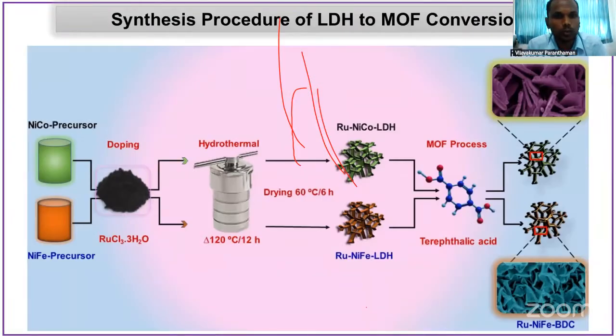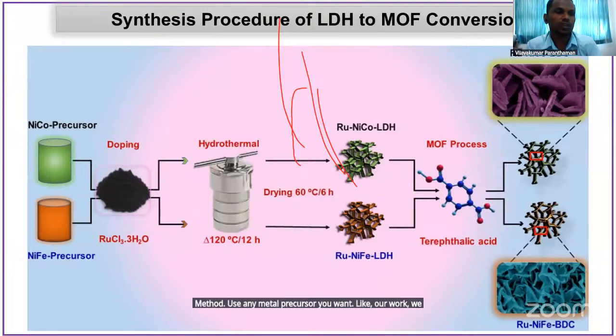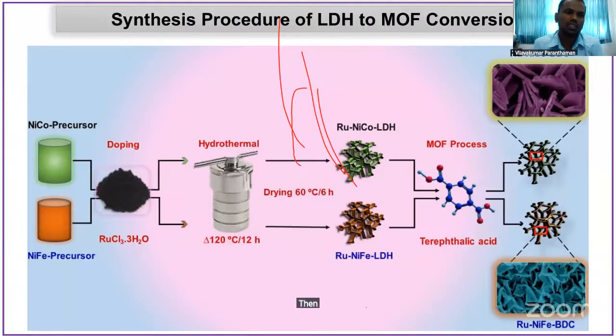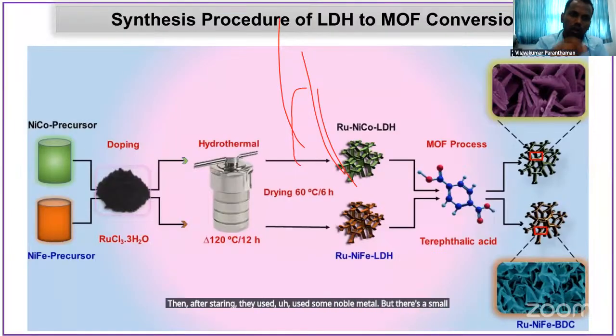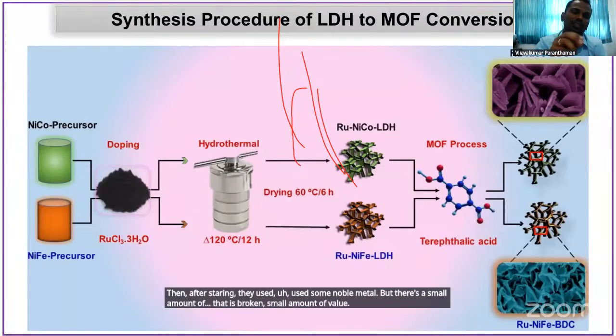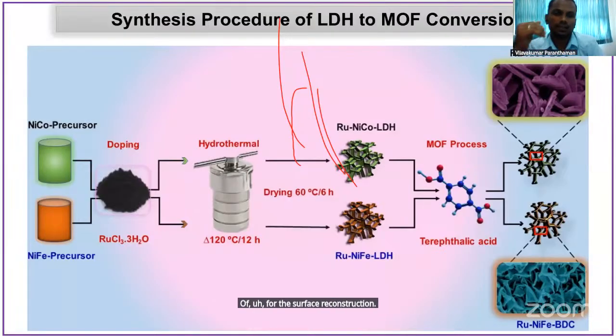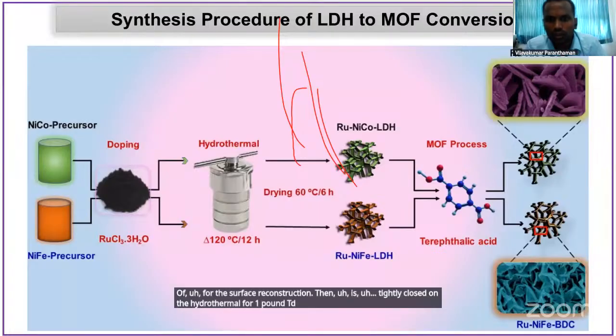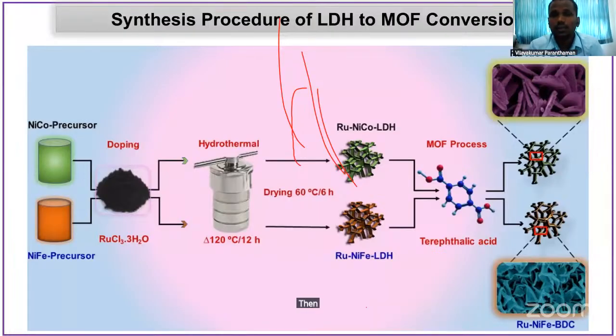This is a very simple experiment, the same chemical approach, the hydrothermal method. Use any metal precursor you want. Like in our work, we have used nickel, cobalt, and nickel and iron precursors. Then after stirring, we used some noble metal, a small amount of Ru doping for the surface reconstruction. Then it is tightly closed in the hydrothermal reactor at 120 degrees Celsius for 12 hours. After gradual cooling, drying at 60 degrees Celsius for 6 hours, the LDH structure is formed.